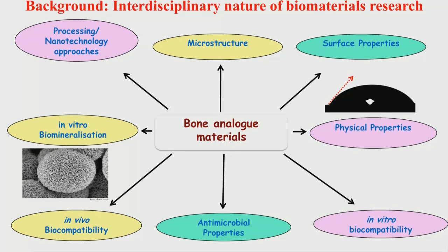Now, in vivo biocompatibility is to be assessed using an appropriate animal model. Since bone has hydroxyapatite as one of its inorganic phases, if some material does not have hydroxyapatite as one of its microstructural constituents, one of the very important things to see is whether this material can induce calcium phosphate nodule formation when it is immersed in simulated body fluid over a certain time period, which can be a few days to a few weeks.